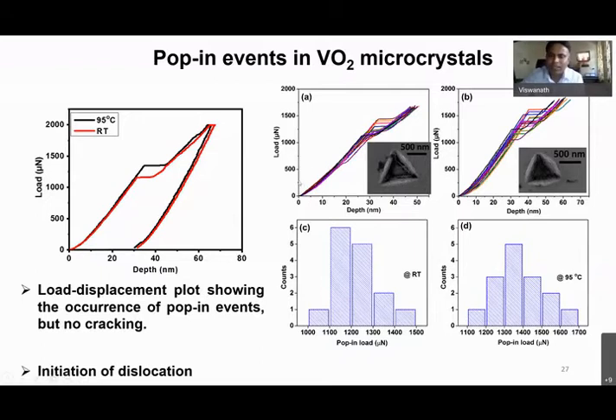But in this case, we are mostly triggering the phase transformation by the temperature. And we looked at the pop-in, exactly what is the pop-in load and so on. We found there is a statistical difference in the pop-in load between the metallic and insulating phase, at least around 1300 to 1500 micronewtons of load. In the absence of any cracking, we think it is maybe due to the initiation of dislocation.